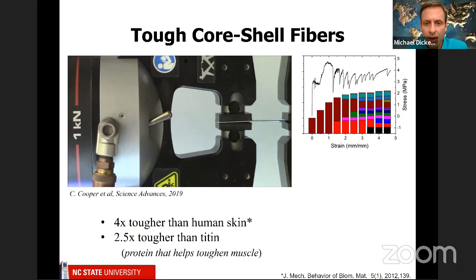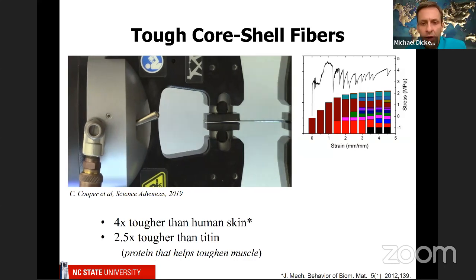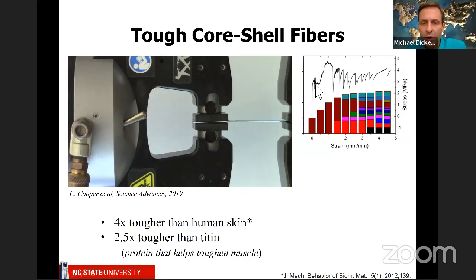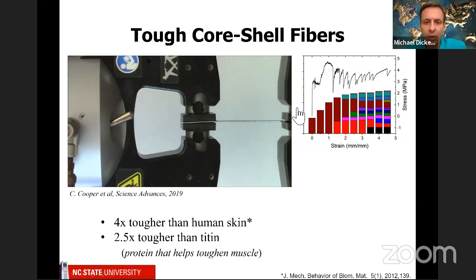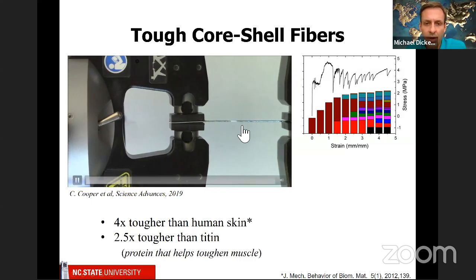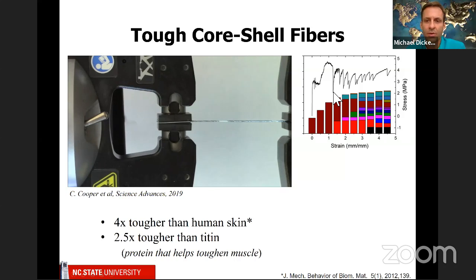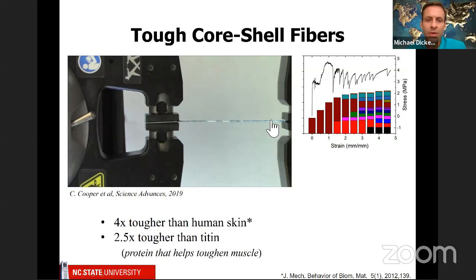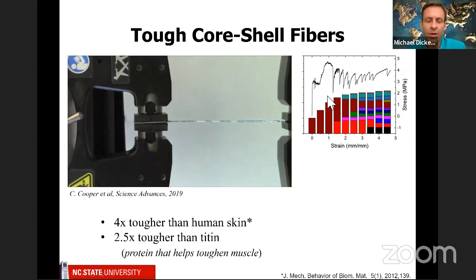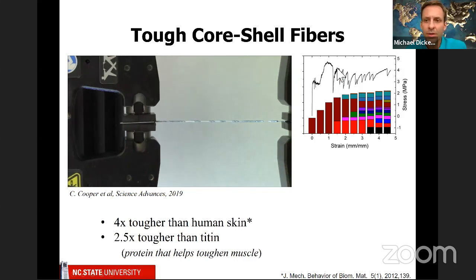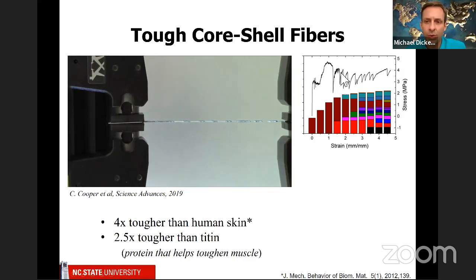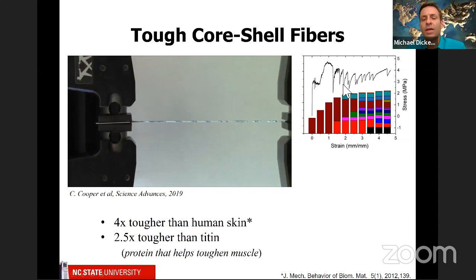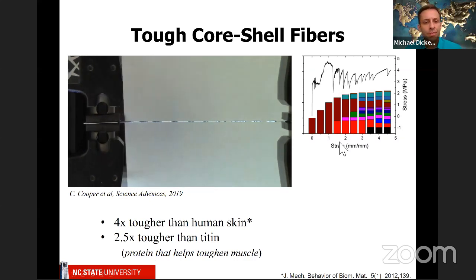I'll play it. So pull on it, and the initial slope is huge because you're pulling on metal. And then at some point it will break, and you'll see it break here. When that breaks, the stress momentarily drops. But then there are these bridges of polymer, and every time it breaks, it basically goes to high stress again, breaks, goes to high stress, breaks, and it does this multiple times.